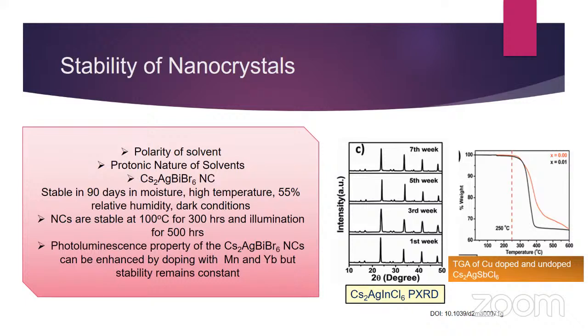So basically the stability of the nanocrystal can be tuned by changing the polarity of the solvent and the protonic nature of the solvent. And this Cs2AgBiBr6 nanocrystal showed stability up to 3 months in moisture, high temperature, and 55% relative humidity. And these nanocrystals are stable at 100 degrees centigrade for 300 hours. And if you also illuminate for 500 hours, still they are stable.